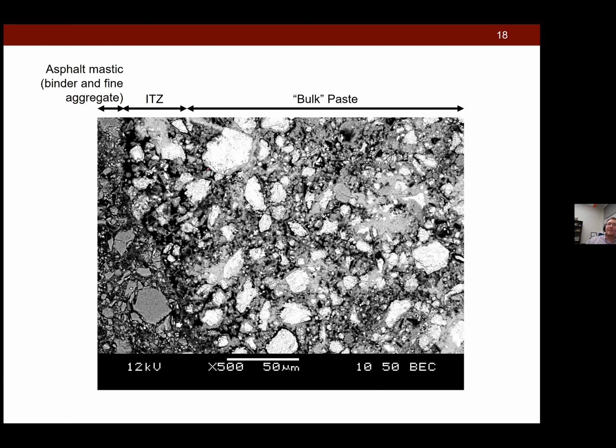This was a 1-day sample. You can see there's quite a bit of porosity. But already just looking at this image, right? So you can kind of see where this asphalt mastic is, right? And you can already see very close to the interface, already just visually, it appears to have a fairly high porosity relative to the bulk.